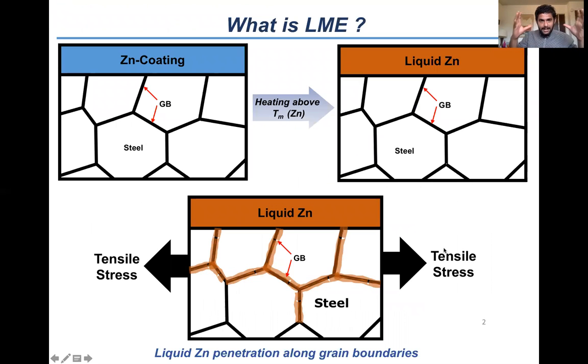If you have a zinc-coated steel, the zinc coating typically has a lower melting temperature than that of the steel. When you heat the steel to a temperature above the zinc melting temperature, there is liquid zinc on top of your solid steel. Now in that condition, if you're applying a tensile stress, then liquid zinc from the coating starts penetrating into the steel via the grain boundaries of the steel, weakening the steel, resulting in the formation of cracks in the steel.